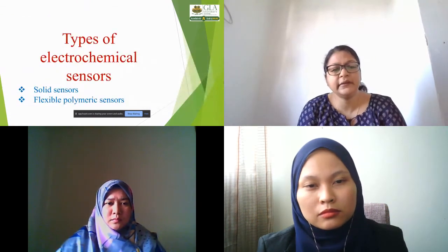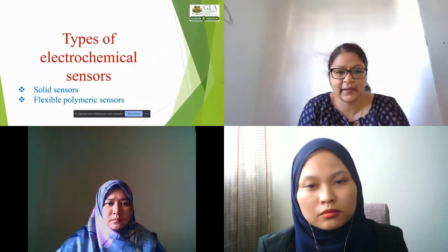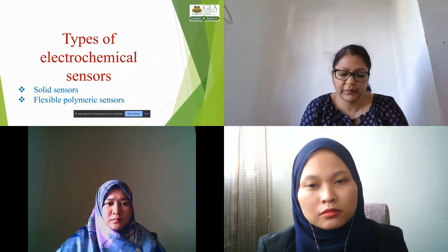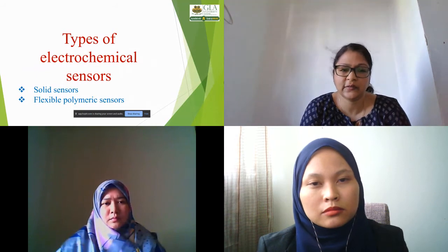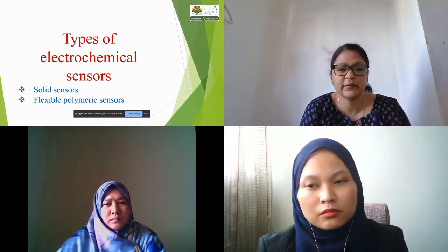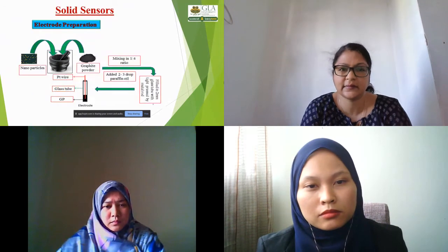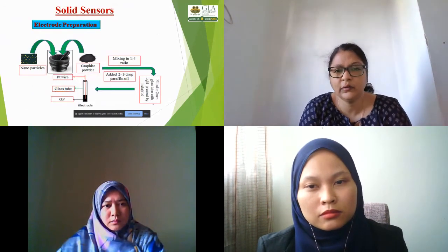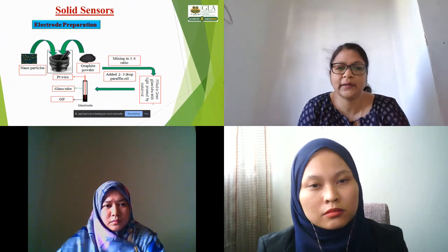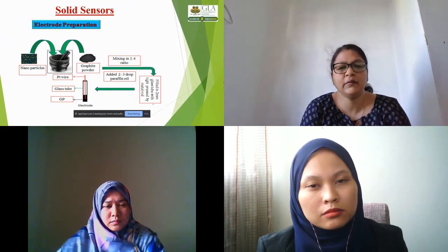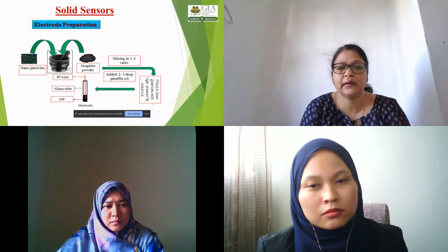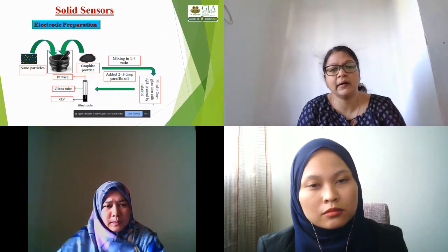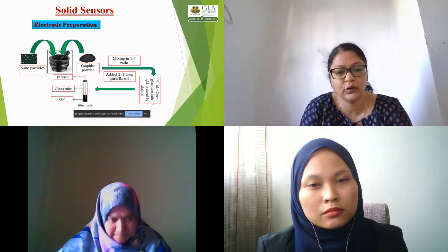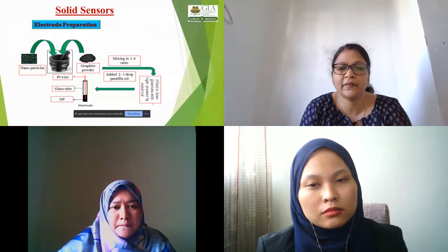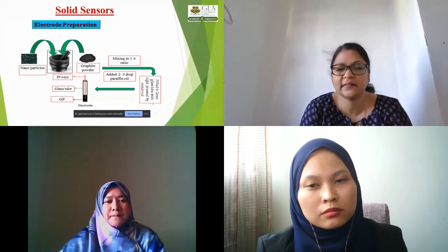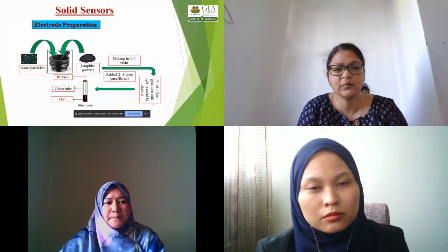Generally, sensors are divided into two main classes. In our team, we initially used to work on solid sensors, but in this project we moved on to flexible polymeric sensors. The solid sensors used the nanoparticles that we synthesized, which we would mix with graphite in a mortar and pestle in the ratio of 1:4, and then using paraffin as a binder, make it into a paste and insert it into glass capillary tubes to make these solid electrodes.